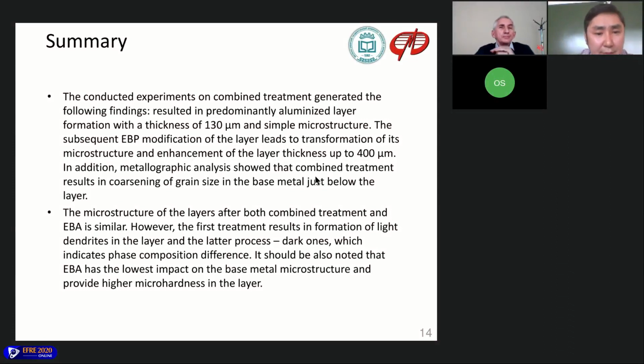So I conducted experiments on combined treatment and generated the following findings. Combined treatment resulted in predominantly aluminized layer formation with a thickness of around 130 micrometers and simple microstructure. The subsequent EBP modification of the layer leads to transformation of its microstructure and enhancement of the layer thickness up to 400 micrometers. In addition, metallographic analysis showed that the combined treatment results in coarsening of grain size in the base metal just below the layer.